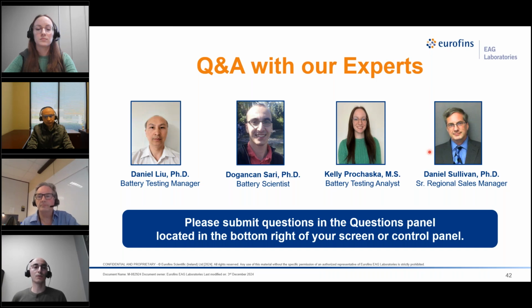This is where it is really important to have good communication with the client and also get as much information as possible related with the cell and the cell components. That's what we do in the beginning of each project. We discuss these and then try to detect the appropriate technique for that particular request. Most of the time it is good to use EDS to get the composition of different elements in that component, but EDS cannot detect lithium, obviously. So we need to use other techniques to see the lithium content of that component.